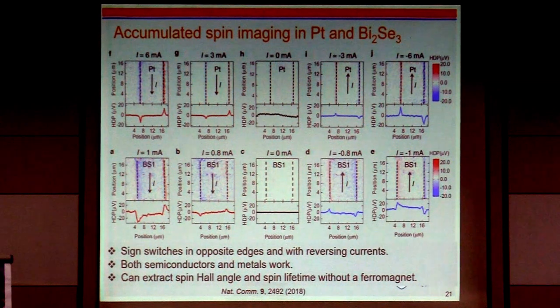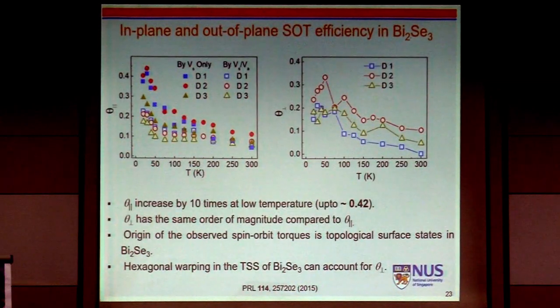So this is coming from so-called hexagonal warping. In real materials, our materials are not ideal, and it's heavily doped. So the Fermi level is way above the Dirac point. At that point, the Fermi surface is distorted. It's no more circular. Okay? It's a hexagonal shape. And depending on the K vector, we can see this so-called out-of-plane spin polarization.